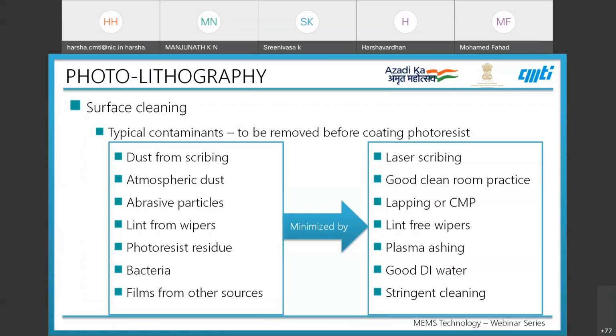Photoresist residue present from the previous step can be cleaned by plasma ashing process. Bacteria could be avoided by using good DI water of grade 1, and films from other sources can be avoided with stringent cleaning.